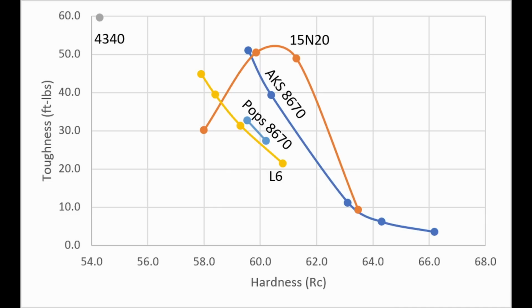So if we compare all those steels that we talked about, L6 and the POPS 8670, that's after I improved the machining and the heat treatment of the steel, they are kind of in the 20 to 30 foot-pound range at 60 Rockwell. The Alpha Knife Supply 8670 can get as high as 40 to 50 foot-pounds around 60 Rockwell, and 15N20 can be around 50 foot-pounds, even a little above 61 Rockwell. So 15N20 got the best hardness-toughness balance. The Alpha Knife Supply 8670 just a touch below. And so maybe the POPS 8670 isn't so much bad as it is just very good, while the Alpha Knife Supply version, for whatever reason, is very excellent.